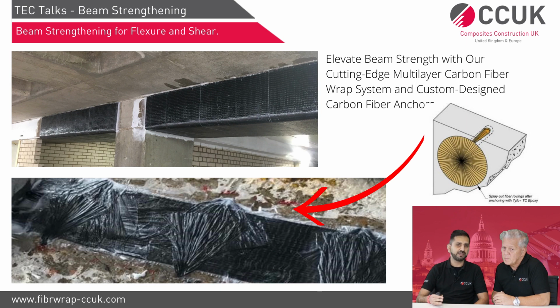So we strengthened these beams by applying FRP at the underside for sagging moments, also on top, which we could see in the bottom left image. So that's the strengthening on top of the beam or on top of the slab. And the anchors are shown there. They were applied to justify a check in TR55 design, which was for shear crack induced FRP separation. So to justify that check, if that check fails, which means you need to confine the FRP,